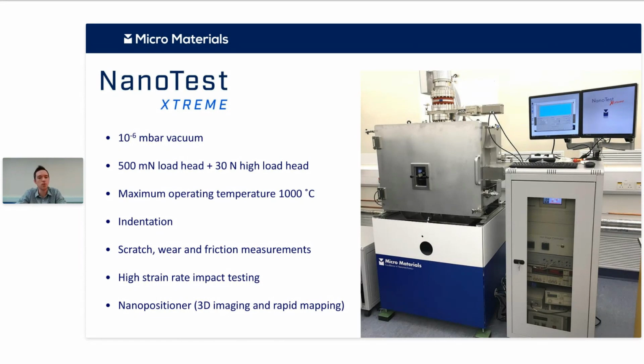In addition to that, we can also include a nano positioner on the system. This is a two-axis piezo stage that allows us to generate 3D images of the sample surface, and also allows us to target very precisely with nanometer resolution, which means we can target submicron features, things like different phases in superalloys or even grain boundaries in ceramics. And again, that is also compatible with the high temperature capability of the system.